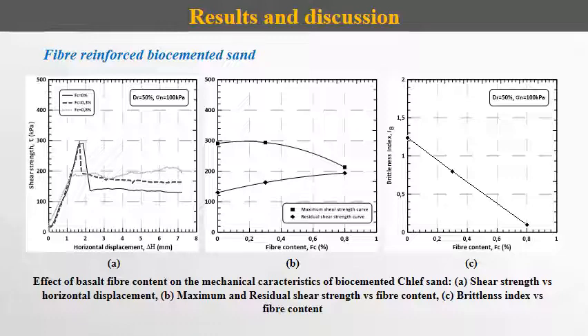The maximum shear strength values recorded at fiber contents of 0, 0.3 and 0.8% were 298, 293 and 213 kPa respectively. Inversely, the inclusion of basalt fiber to biocemented sand samples increased the residual shear stress. The residual shear stress values recorded were 130, 163 and 194 kPa at fiber contents of 0, 0.3 and 0.8% respectively.